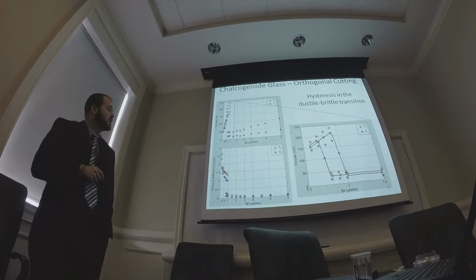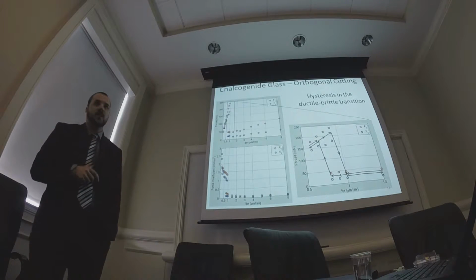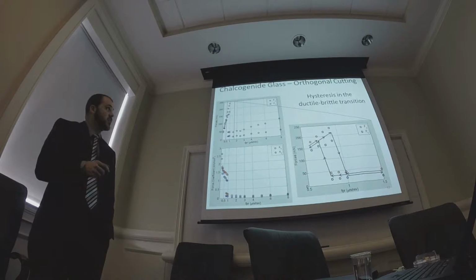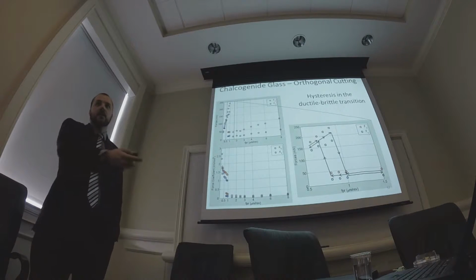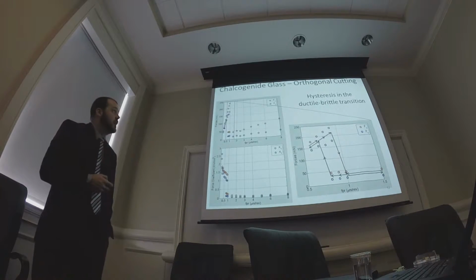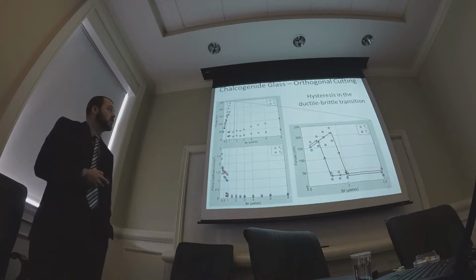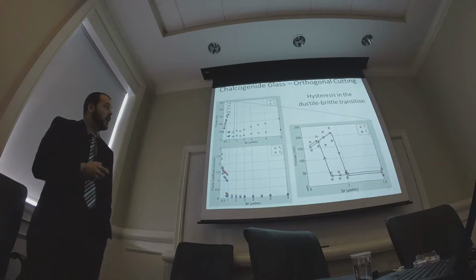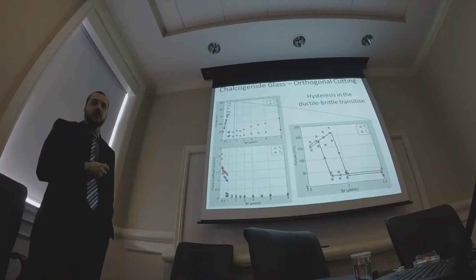So I thought to myself, okay, I did the sequence from left to right - what happens if I do it right to left? So I started with a brittle surface, or what I assume is brittle fracture dominated surface, because we cut the material away every time. Inspecting the surface each time would be time intensive and longer than would be worth taking these tests for. So I started working my way this way, and instead of jumping from 1 micron up to 100 nanometers, I stayed down here - 900, 800, and at 700, I jumped.